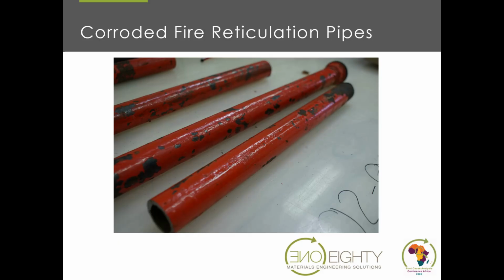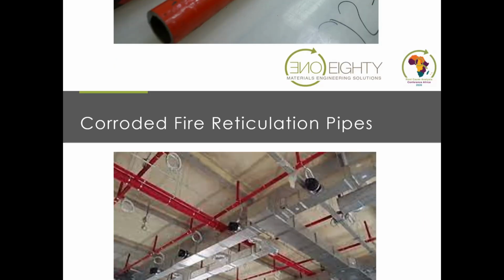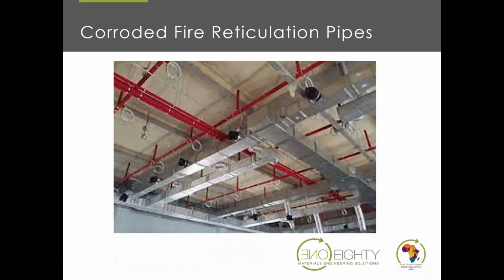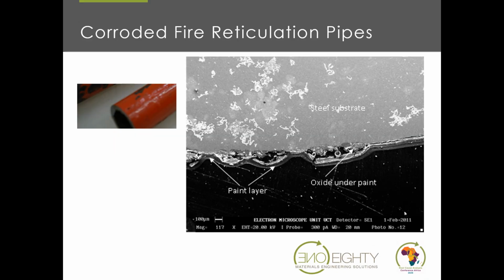So typically, this is what an installation will look like. And yeah, we were provided with a sample. On the right-hand side is an electron microscope image of a sample that's been taken from the pipe. But now we needed to take a sample. There's no point in taking a sample in the corroded area because the damage has already been done. The corrosion obviously occurred because the paint coating failed. We had to get on top of why the paint coating failed.